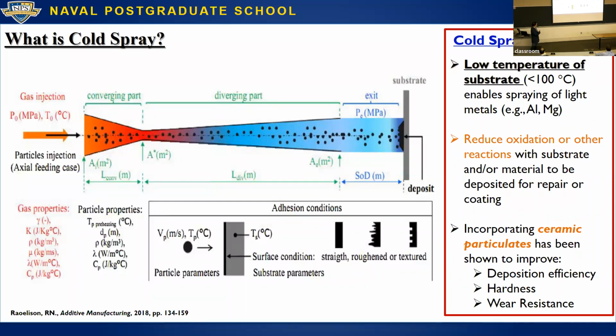Your particles spend very little time in that gas because this is a converging, diverging nozzle that actually makes the flow supersonic. So you're spending on the order of maybe microseconds. You're just trying to heat the gas up enough that it softens. It softens because you are essentially going to take those particles and blast them onto the surface. And when you blast them onto this surface and they're warm, so they're soft, they actually go from being spherical particles into being essentially splats or lamella.